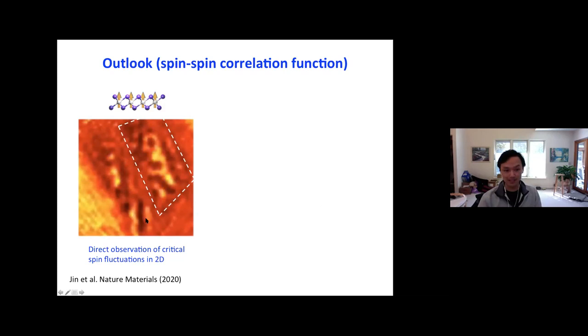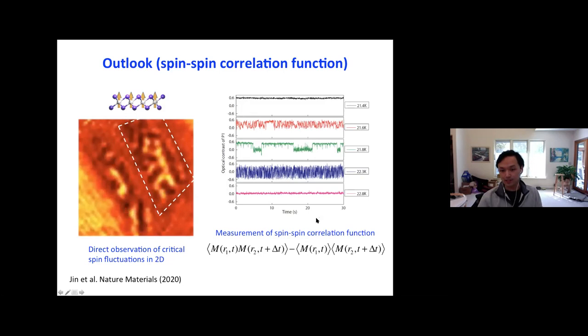So this is a direct video showing a monolayer of chromium bromide near its critical point, and you can see spontaneous fluctuation of the magnetic domains in the system. And you can trace its time dependence. What's important is that we can measure from this data the spin-spin correlation function of the system. And I think it's quite a powerful, interesting method